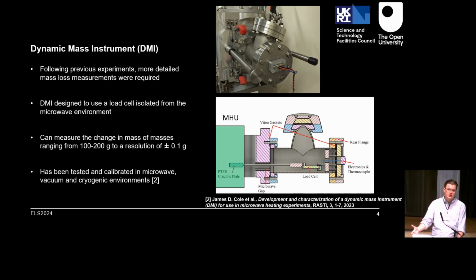So I looked into building a mass instrument that could measure the real-time mass loss from samples, meaning that each sample I knew was fairly consistent, and I could change the heating time and look at how the mass loss changed over time. I did so by using a load cell, and I isolated it from the microwave system using a very small gap, and then using microwave transparent materials from there. It can measure masses between 100 to 200 grams to a resolution of about plus or minus 0.1 grams. All the gory details of the calibrations and the preliminary experiments can be found in the paper mentioned here, where I essentially made sure that it could work at the different conditions I required for my experiments.